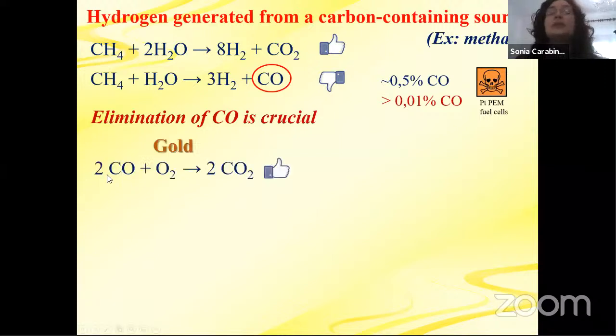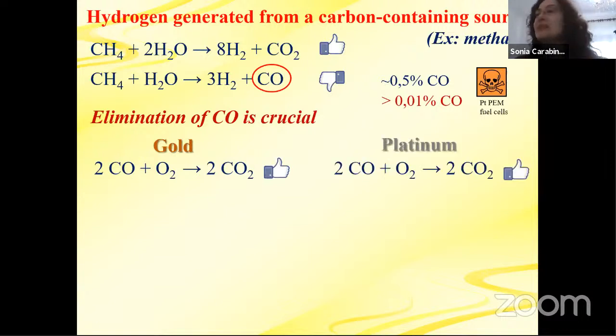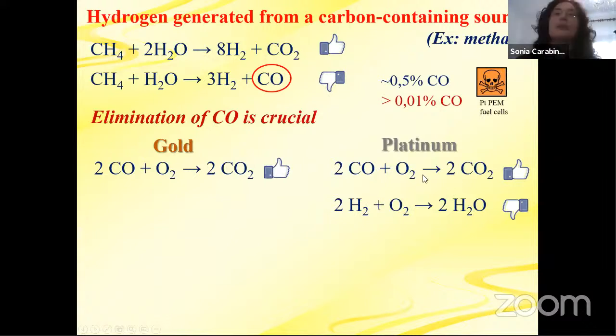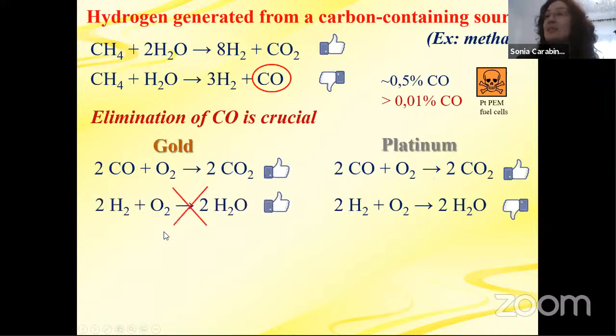And gold, what happens? Gold is very efficient for this CO oxidation reaction, as we saw already. So that's quite good. However, platinum also is quite active. It does the same, although not at the same temperatures, a bit higher temperatures, but okay, it's still active. But the problem of platinum is that it oxidizes everything, not just CO, but also the hydrogen, forming water, which is not good because we want hydrogen. We don't want to convert it back to water. That's the problem. So the advantage of gold is that it's not active for this reaction. It's in fact very selective.